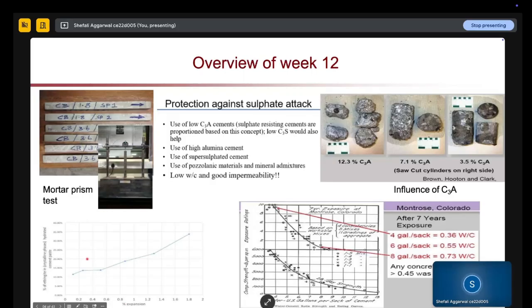So this is another type of testing which has been done in lab. In this case, we are showing how expansion changes with the percentage of ettringite. This is the result for the mortar prism test. If you have, let's say, 10% of ettringite, then you have a lower expansion. But if you have 30% of ettringite, then your expansion rate will be 1.8%. So this is a curve which we will get from the mortar prism test.